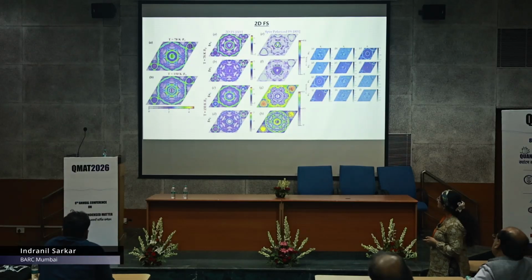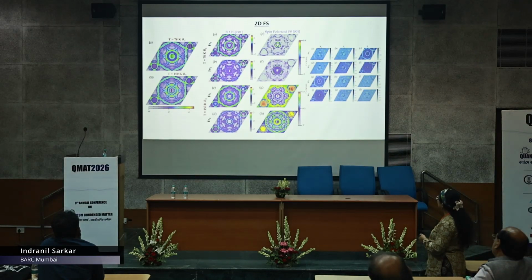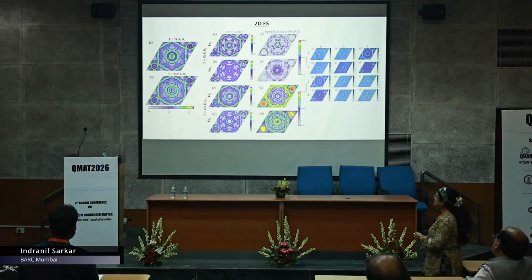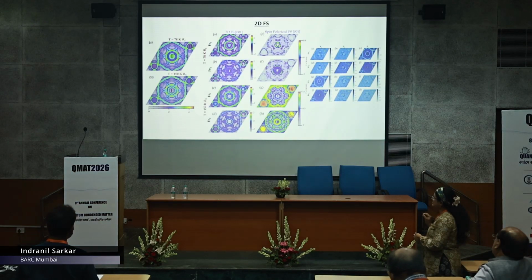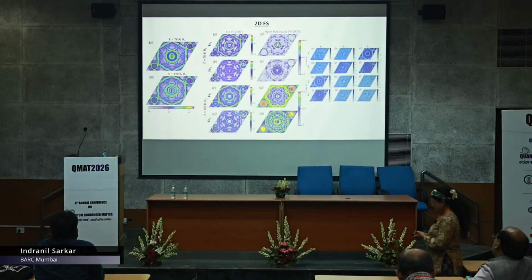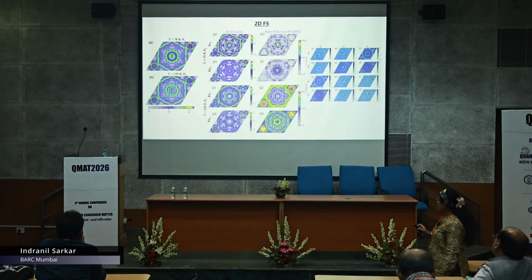And when we have looked at this 2-dimensional Fermi surface, you can see that the site projected Fermi surfaces are very different with temperature and also with field direction, and for Fe1 and Fe2. There are a lot more details which I do not have much time for, but what I can say is that around the gamma point, with increasing temperature, the footprint of that pseudo gap opening is there. That pseudo gap is opening, and that's why the electron smearing has gone, and that has resulted in a kind of hole pocket here.